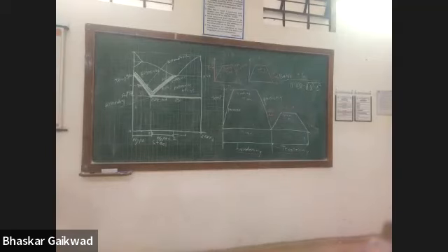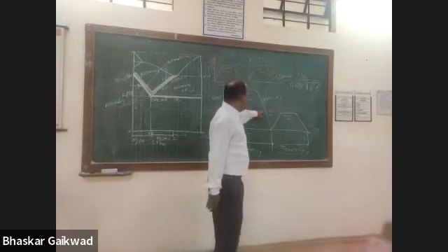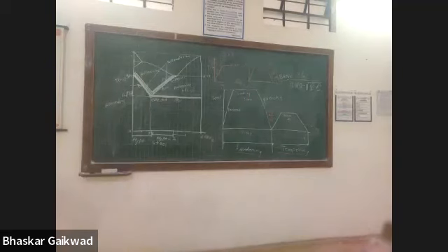After quenching it will bend. If drastic quenching is there, drastic bending will be there. If that type of distortion occurs, you can change the quenching media. Here I have given water, oil and air. If you go for water quenching and the cross-section area is large, there is a possibility that area will bend, a small distortion.